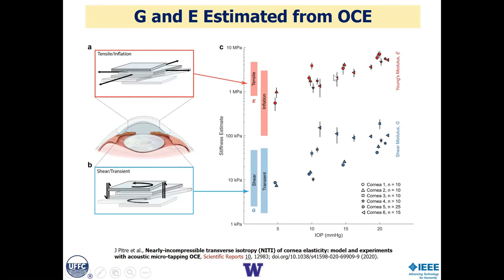Young's modulus E is in this megapascal range. This shear modulus is in the tens of kilopascal range. And we can measure this over the IOP and get the nonlinear characteristics. So for the first time, we can use non-contact wave field measurements to get the elastic moduli, which can be used to predict shape, which is the fundamental property needed for clinical interventions.